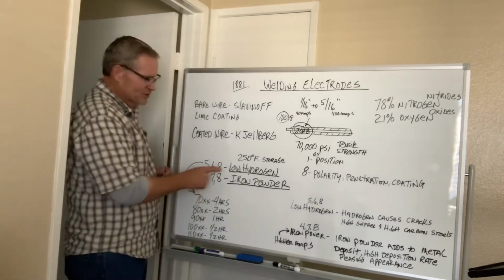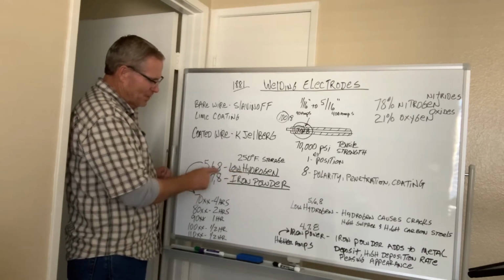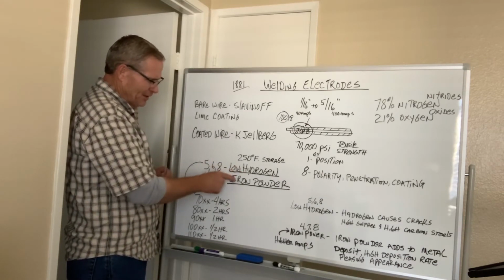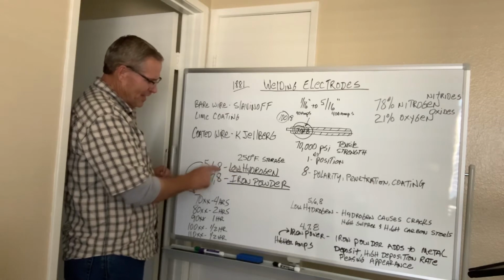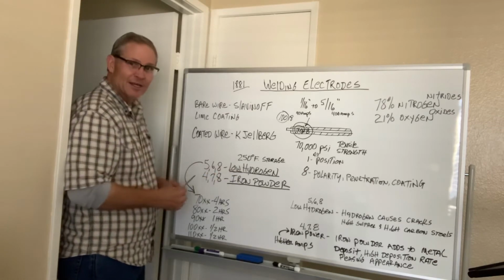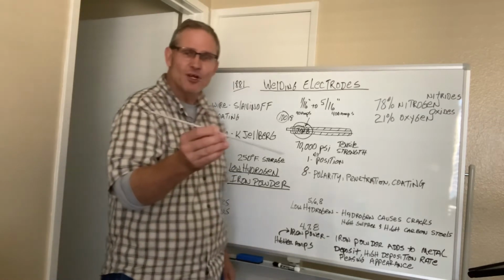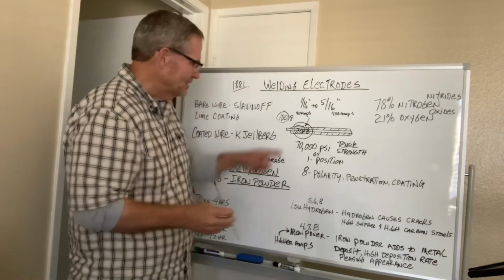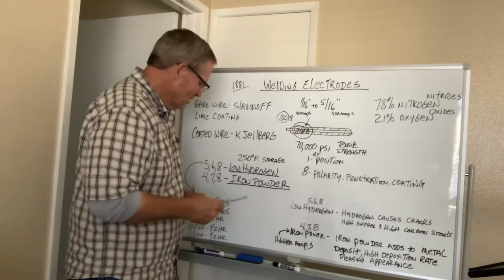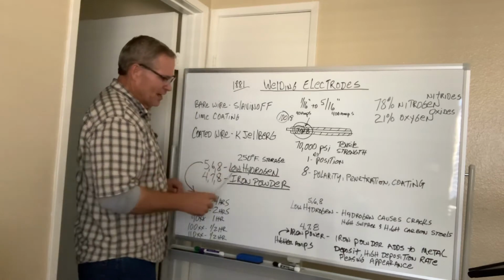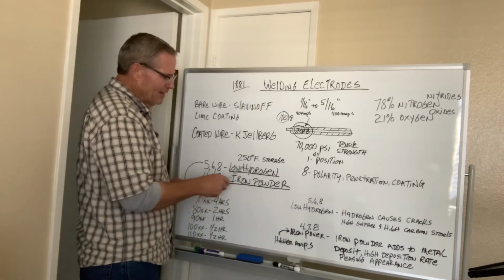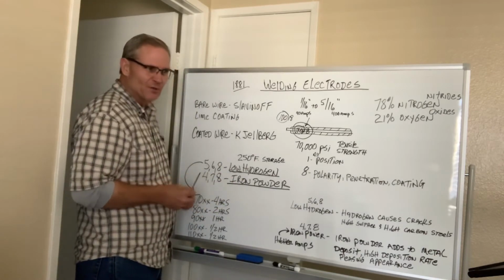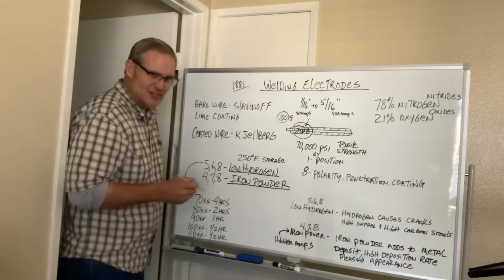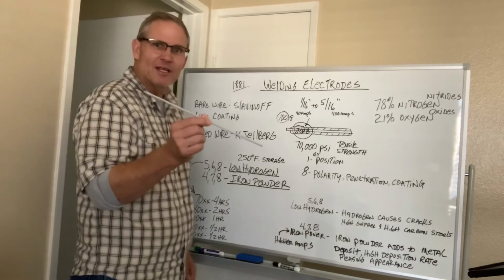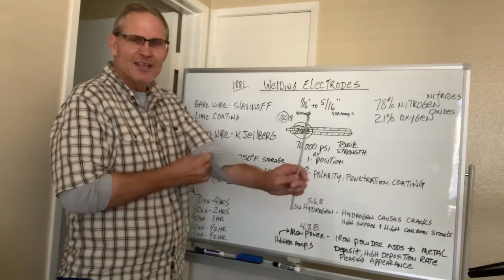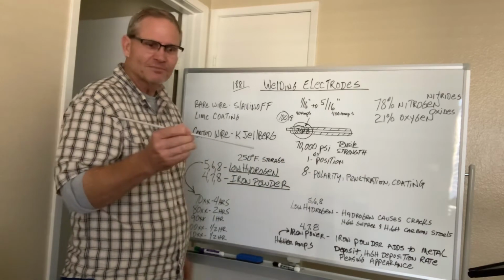Now, you might have noticed there is an electrode that has both iron powder and low hydrogen, and that's the one that ends with an 8, which happens to be the one that I was showing you earlier, 7018, and it's the one that I'm demonstrating on. So this electrode uses more amperage, and also it's a low hydrogen electrode. And I would suffice to say that this is the most common electrode that's used in the welding industry itself,